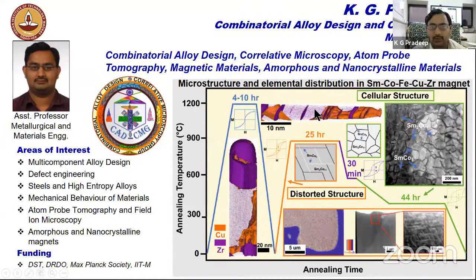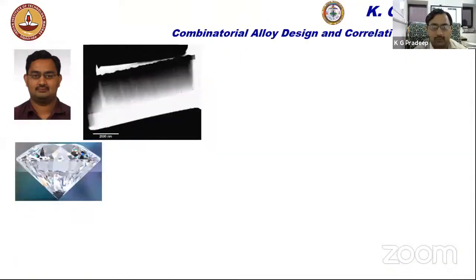So this already gives us the first fingerprint of how the defects are organized and how this organization is changing the magnetic behavior, as you see from this ordered defined structure and the hysteresis loop associated with it. So one can directly connect the microstructural features with its properties in a straightforward correlation. So coming to the center's objectives, if you now go back and take, for example, a nanocrystalline diamond thin film. Now we have done this kind of a characterization, so we know it's a diamond.